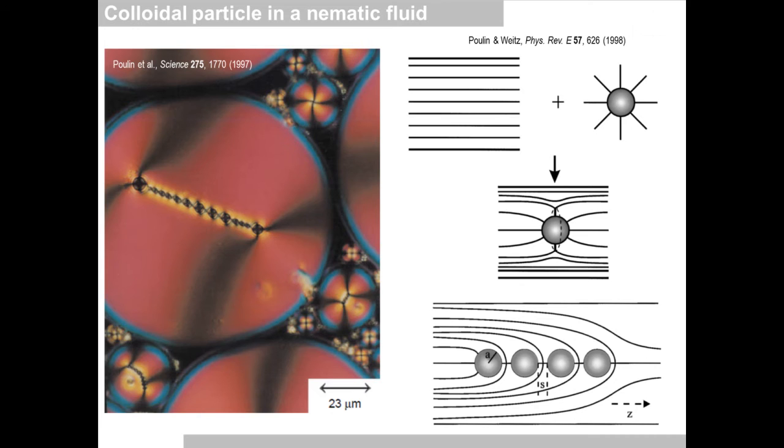What will happen when spherical particles are dispersed in an anisotropic fluid, such as a nematic liquid crystal? In the idealized scheme of the nematic phase, the rod-like molecules would align roughly along the same direction. If the molecules are anchored on the dispersed particle, the director field will be deformed, and the consequent orientational conformation of the molecules would result in a topological defect formation around the particle.